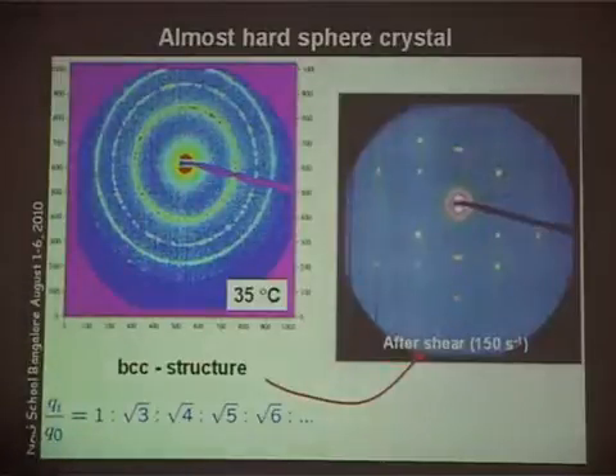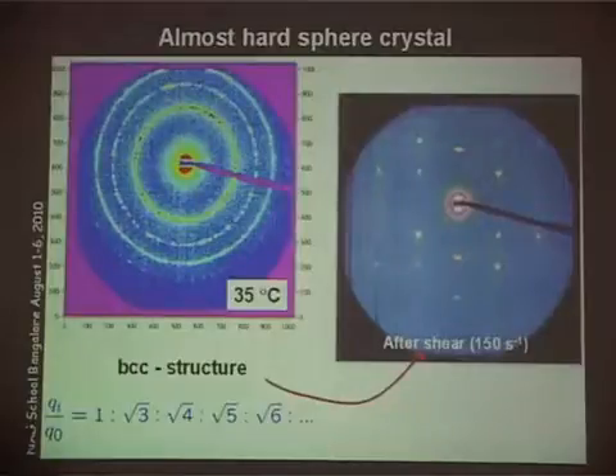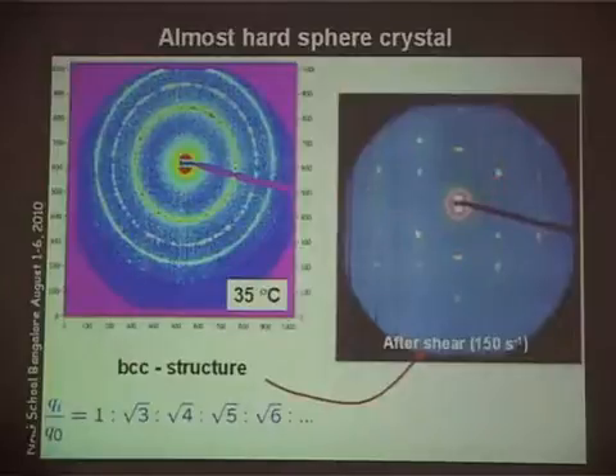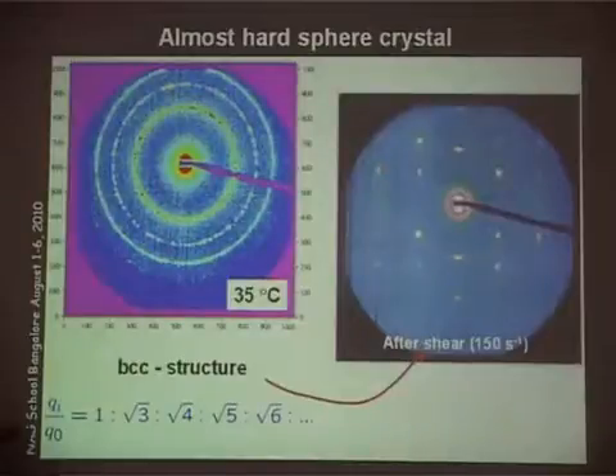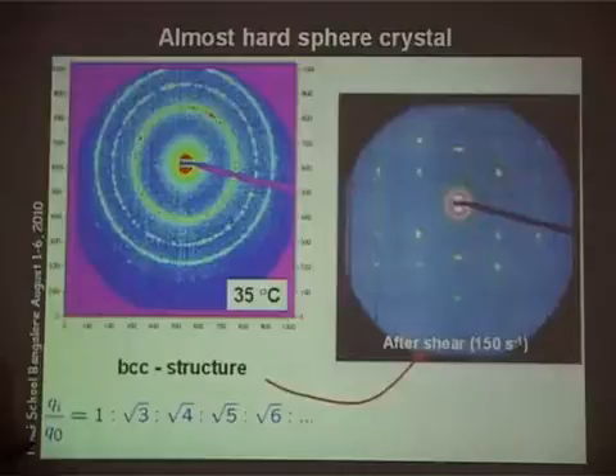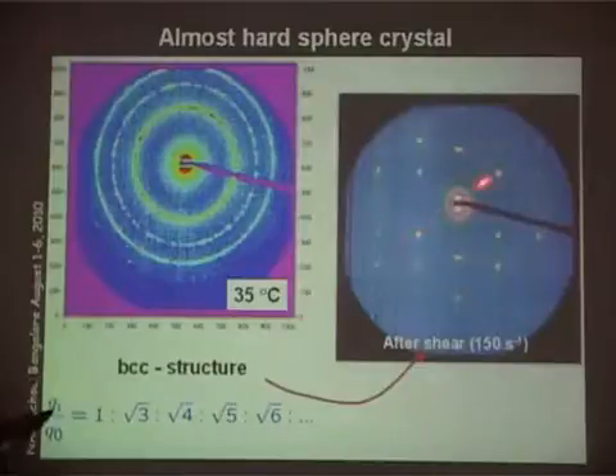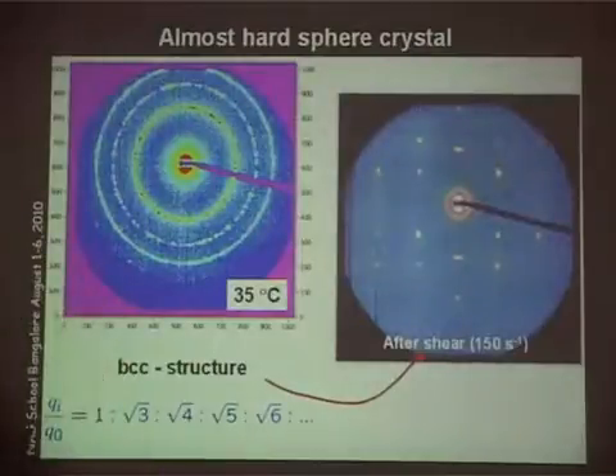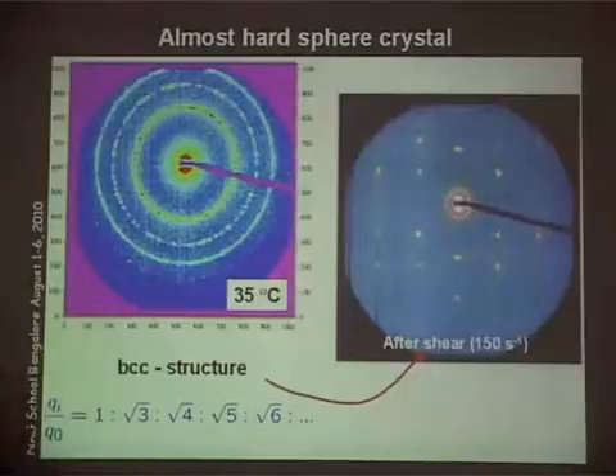So I sheared it in situ, online, in my system. I stop and I measure, and I get these very nice diffraction peaks, and that means I now have only a single crystal in the system. Funnily enough, my BCC pattern should only give me 2 diffraction spots, but I get 4 at the same distance. You see that these 2 belong together and they are stronger, and that simply means I have 2 twins in the system. So I also see some symmetry. I have twinning in the BCC crystal.